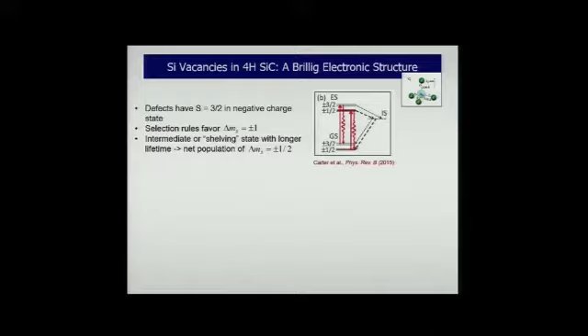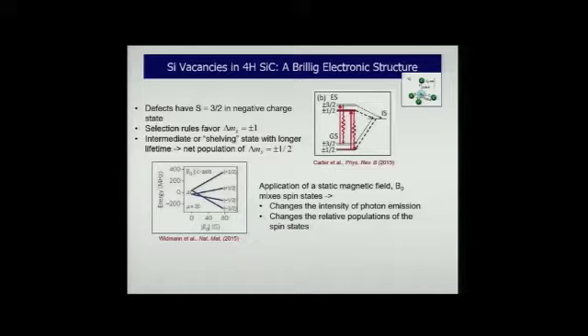So we should expect that there may be a natural way of creating a polarization or net spin for these defects. Added to that is that for these spin states, if we were to apply a static magnetic field, B, that magnetic field will mix those spin states, plus or minus 3/2, plus or minus 1/2, as roughly indicated by this diagram, which shows the energy of the different spin states as a function of this B0 in Gauss. What the two together mean, this sort of shelving and